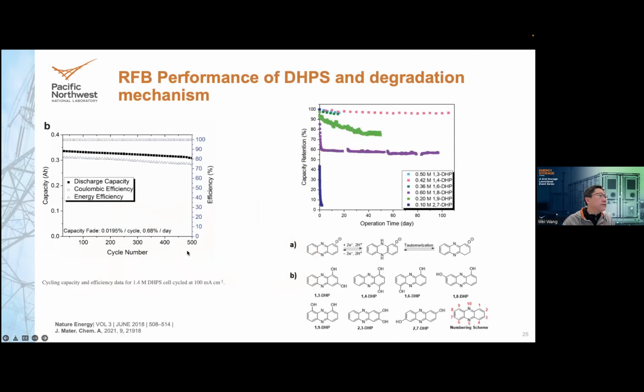This material is not very stable compared to some of the later materials we discovered. And we also did a study on the degradation mechanism. This is actually a very important topic that has not, in my opinion, collected enough attention in the research field: how we can make the molecule more stable in long cycling, because flow batteries, if we want to support the electric grid, need to have stable cycling for many, many years. So this is one of the degradation studies showing different substitution patterns and how that will affect the stability of these different molecules.